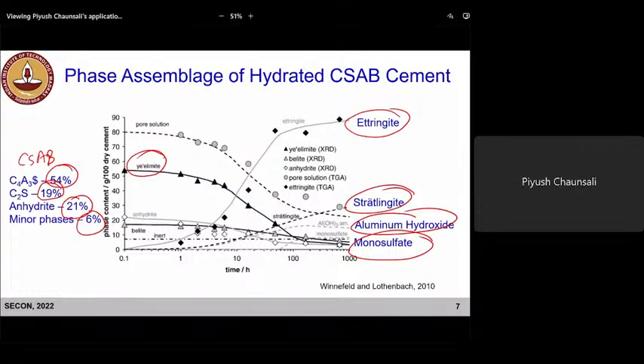And in this plot, you see that the thermodynamic modeling was able to predict how much of these phases will form, and this was verified using X-ray diffraction and TGA.